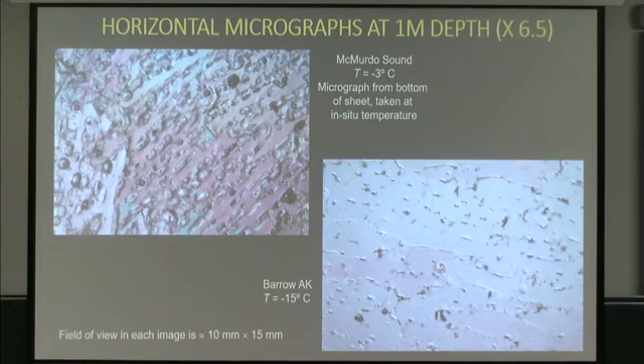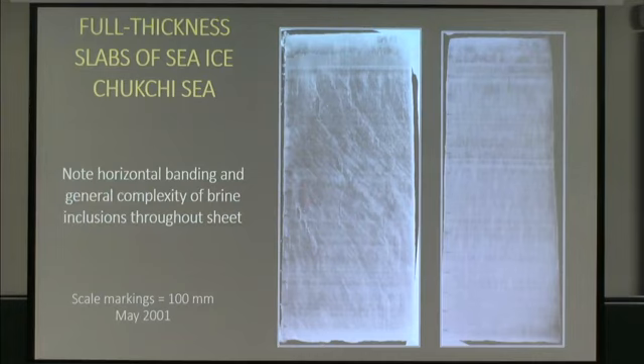Conversely, at -15, there's this from the phase diagram. You have the brine inclusions close up considerably at low temperature. So you have a really different level of perforation of your ice, the ice matrix, that's very temperature dependent. And I'm not going to get into too many details on that here. I'm going to focus more on the anelasticity and the creep. But it's a real key thing to be aware of.